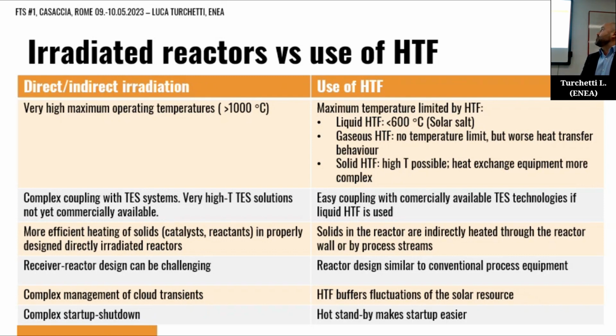When we use an HTF, a heat transfer fluid, the maximum temperature is limited, of course, by the stability and applicability of the heat transfer fluid. And when it comes to the current molten salt mixtures that are used in CSP plants, this is below 600 degrees Celsius as wall temperature, which means a bulk temperature in current installations of up to 565 degrees Celsius.